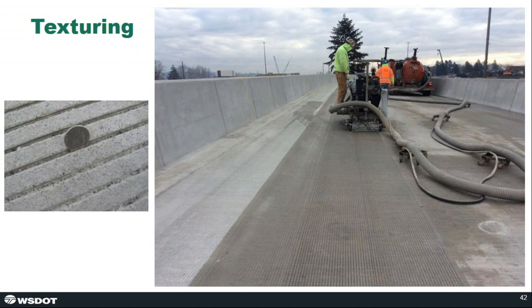And this texturing provides traction to the bridge deck surface. And it's all done after the curing, after the cure is complete, which is nice. When we were tining the bridge decks transversely, that was just another operation in the bridge deck construction process that has potential to go wrong and can delay the installation of the cure system at times.